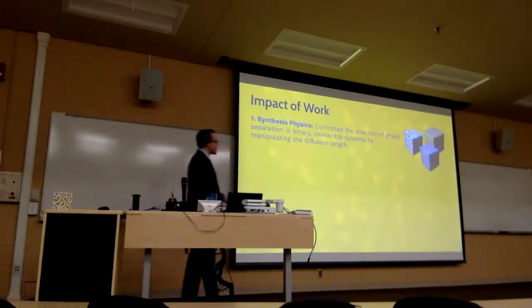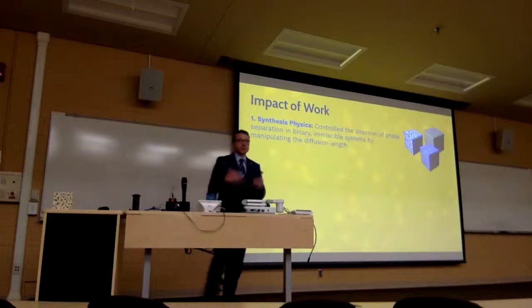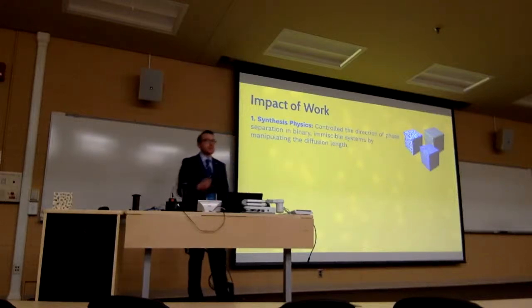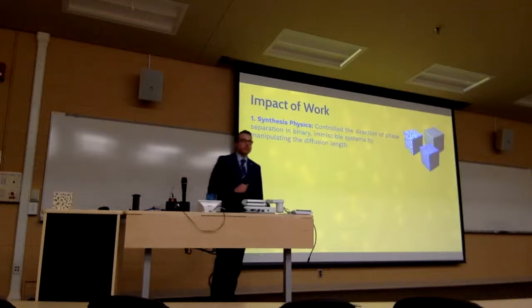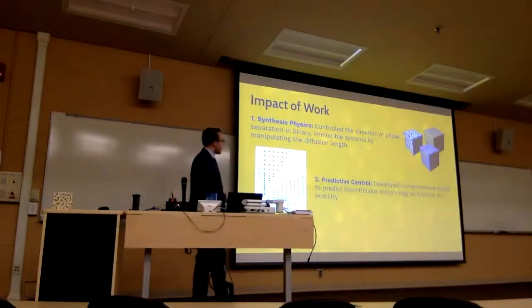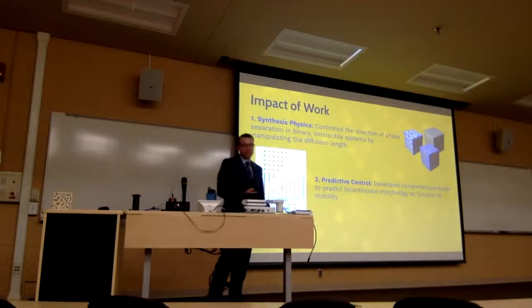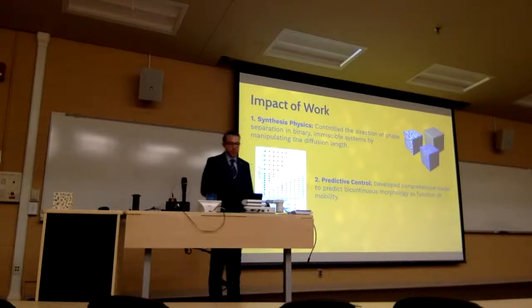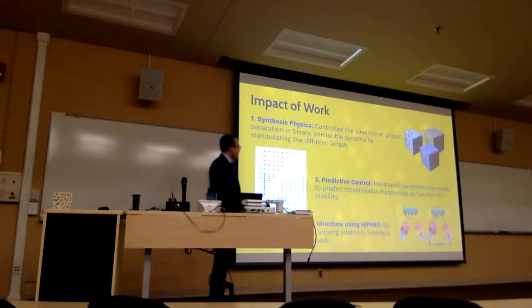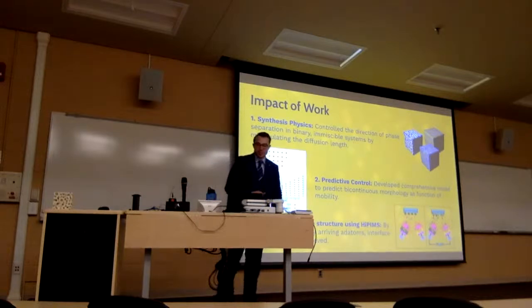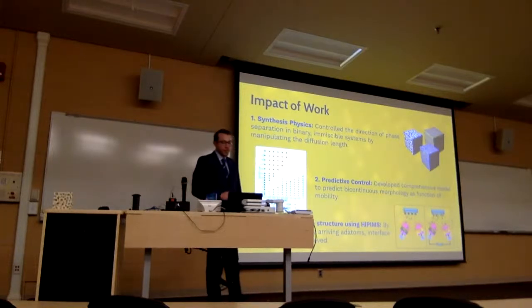So I've described to you a lot of different topics today, and what I'd like to do is just describe a summary of those results. So first thing is that synthesis physics, we actually were able to control the direction of phase separation by manipulating the diffusion length during deposition. We developed predictive control over the morphology by extending our phase field simulation model in 3 dimensions. What I didn't show in this work is that we actually developed a new deposition technique known as HiPIMS to control the morphology even further.